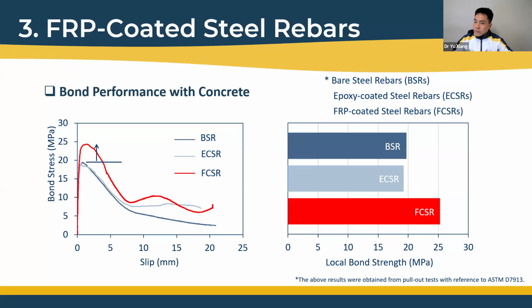We performed the pull-out test with reference to the ASTM standard and found that the local bond strength of epoxy coated steel rebar was about 2% lower than that of bare steel rebar.